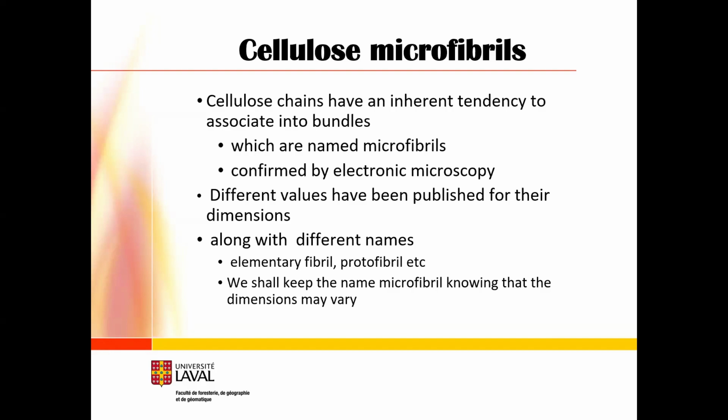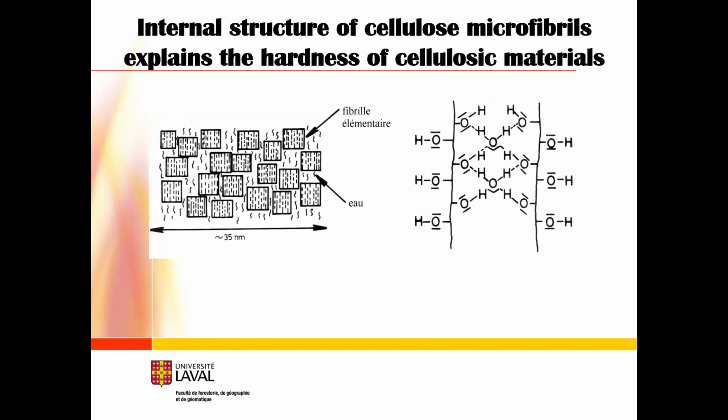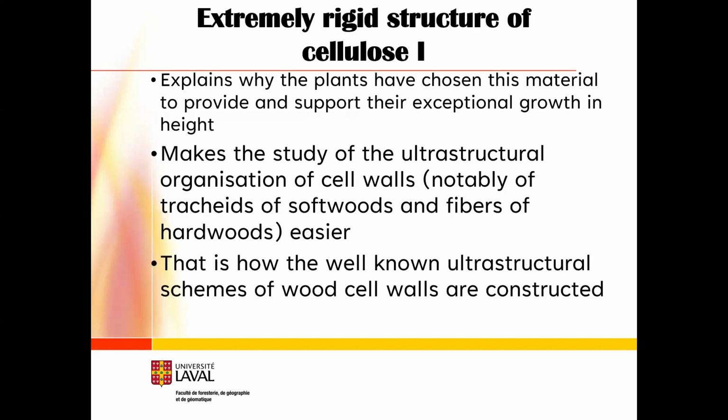The structure of the other types of cells is even more complex, but this is the usual type of scheme that we present, where we speak about the more or less organized domains in the microfibers of cellulose, some of which are really characterized by true crystallographic means, as there are really micelles of crystals.